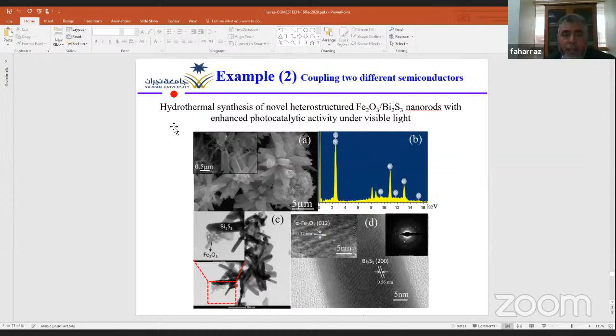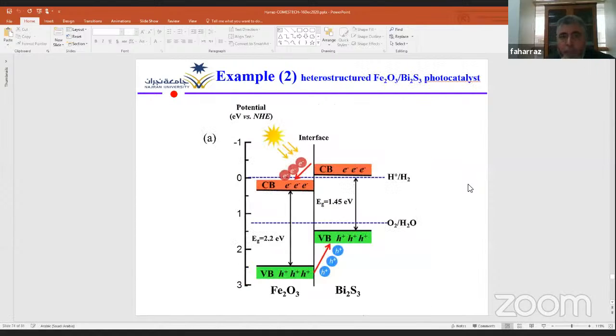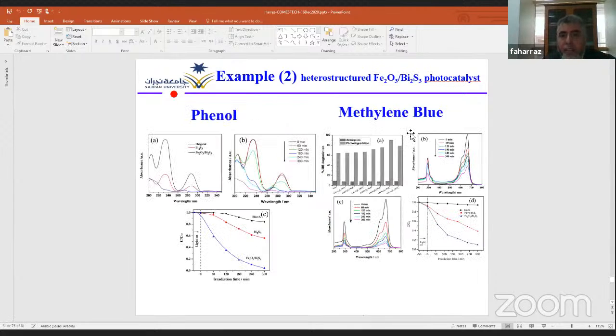The second and last example of this talk is the fabrication of a coupling of two different semiconductors using the hydrothermal technique. We fabricated a heterostructure between iron oxide, hematite, and bismuth sulfide nanorods, and used this hybrid nanomaterial as a visible light photocatalyst. This is the characterization and morphological investigation of our hybrid structure. The interesting thing here is that there is a very nice band alignment between hematite and bismuth sulfide in a way that enhances the separation of charge carriers. Using this heterostructure of iron oxide with bismuth sulfide photocatalyst, we can photodegrade phenol and methylene blue without sacrificing photocatalytic performance.